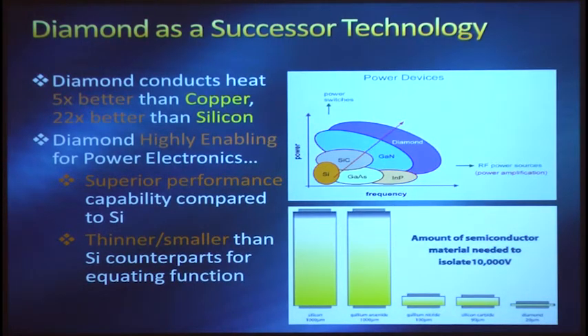But more importantly, and more specifically for power electronics use, diamond actually has a superior capability because we can put tremendous amounts of power in much smaller area. We can drive it at much higher frequencies. And if we think in terms of the material, just to isolate a specific amount of voltage, it's about 50 times smaller than silicon. So we're using less material, which is more power efficient and more thermally efficient.